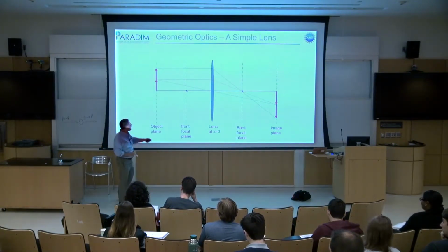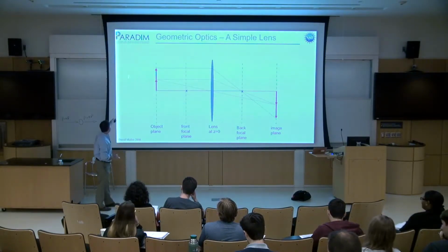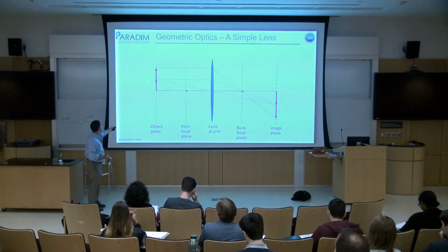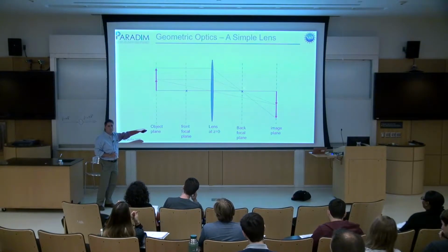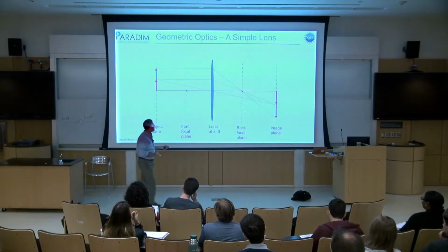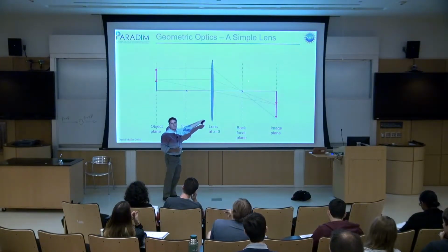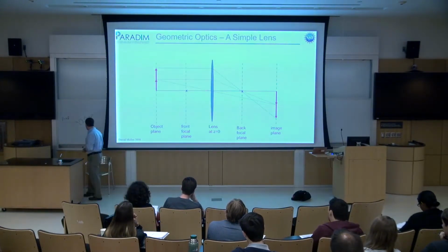And that would have corresponded to rays. Imagine I illuminate my object back over here with a parallel beam of electrons. The parallel beam comes in and hits the object. Those rays that traveled in the forward direction did not deflect. They're going to end up going through the center of the back focal plane. So the way to read off the back focal plane is, if anything appears in the center, that's the unscattered beam, or at least it's the forward scattered beam, because the beam is allowed to pick up a phase shift as it goes through the sample even without changing direction.